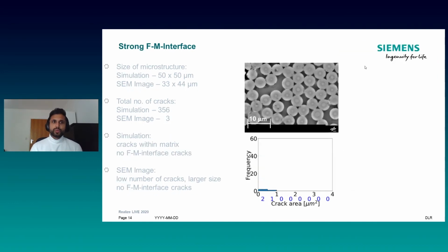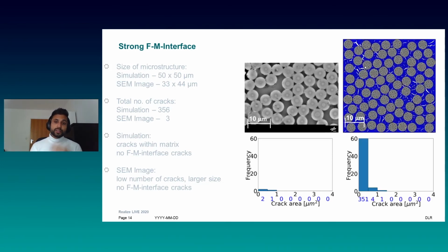What happens if we go to a material with a strong fiber matrix interface? Here we can see there are no cracks or almost no cracks present in the matrix. As you remember from the previous slide, in the carbon-carbon bundle, there are no cracks. The cracks are along the carbon bundles. These are the pore channels where the fluid silicon fills up the holes to react with carbon in the end. And when we compare the simulation results with that, we still see these small cracks.